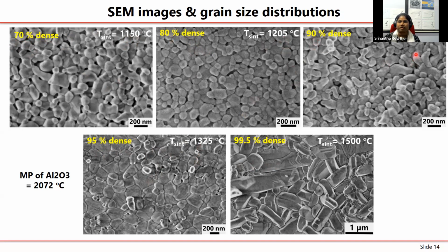Until 1250 degrees Celsius, the grains are of more or less similar size, so there is not much grain growth. However, at 1325 degrees Celsius, you already start seeing the grains coming quite near to each other. The grain boundary area is increasing dramatically, and the grains have also started becoming slightly bigger, so grain growth has started. Then if you sinter at 1400 or 1500, you see very elongated grains in those materials. So these 5 samples were taken for further experiments.